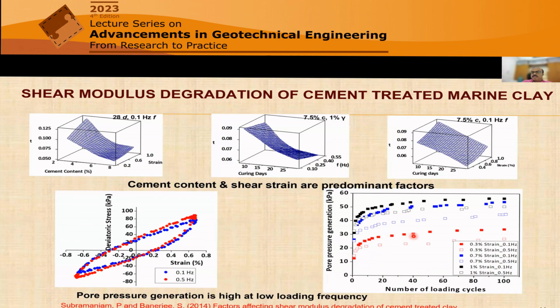The solid points correspond to 0.1 hertz. The hollow points correspond to 0.5 hertz. And as you can clearly see, the 0.1 hertz, the lower frequency, is actually leading to higher development of the pore pressure. And it is consistent for all different strains. At the 1% strain, the highest one, see the solid point in black is at the top, and the hollow points are somewhere here. So consistently, we are seeing that the lower frequency is causing higher development of the pore pressure.